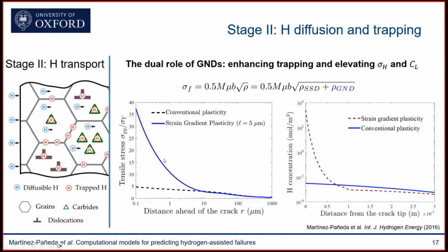You can see these are the tensile stresses ahead of a crack tip. So you have a crack here, and I'm plotting the tensile stress ahead of the crack. And you can see that far away from the crack tip, your predictions using these constitutive models that account for the GNDs, so-called strain gradient plasticity models, coincide with conventional plasticity. But as you approach the crack tip, there's a very significant stress elevation associated with the GNDs, with these plastic strain gradients. So this significant stress elevation near the crack tip, over the critical distance that matters for hydrogen-assisted fracture, is going to drive the hydrogen content near the crack tip as well.